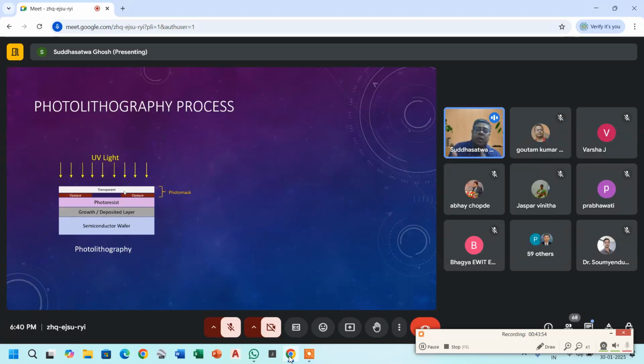The pattern of the photomask is defined by the pattern we want to achieve on the subsequent semiconductor wafer. At a high level, the photomask is placed on the semiconductor wafer, and through the photomask we expose UV light. A photomask has both transparent and opaque areas. If it's a transparent area, the light goes through, and in the photoresist it weakens the bond so that it can later be removed and dissolved. Whereas the areas on the photoresist which are not exposed can be hardened, so that they can withstand the subsequent processes.